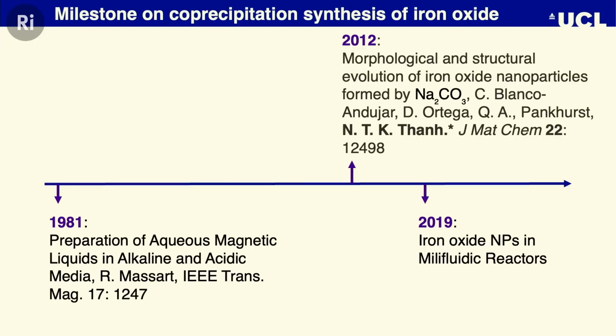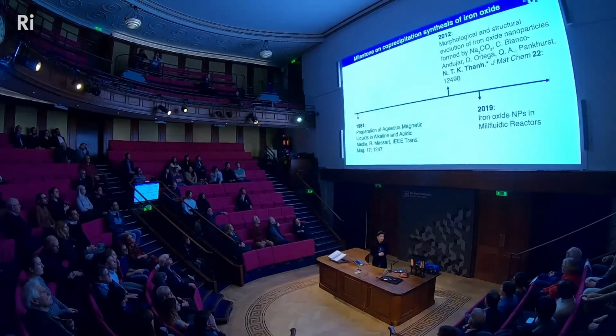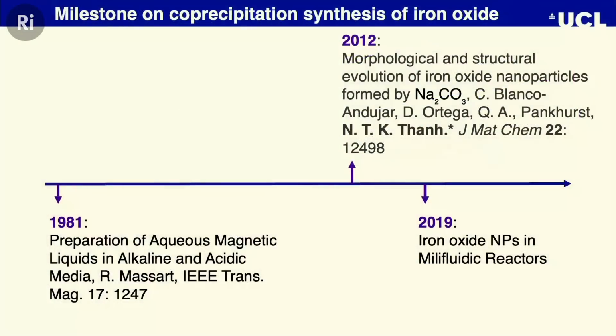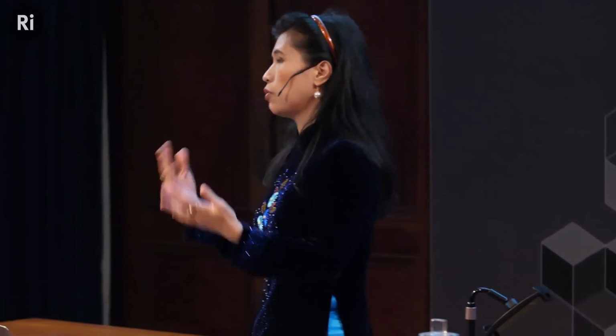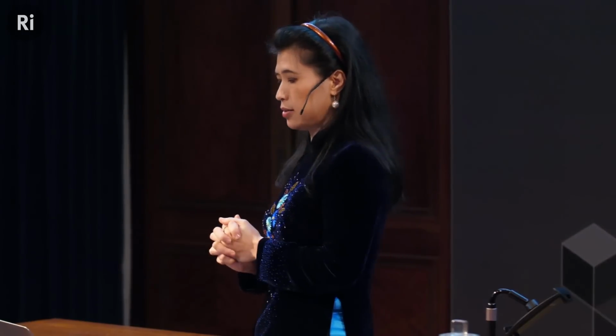Unlike gold, which Faraday made as gold nanoparticle in solution in 1856, it was only in 1981 that René Massart published the paper using two salts, ferric iron and ferrous iron, with ammonia, and he formed the co-precipitation method for forming the nanoparticle. They did the characterization by XRD, and they also found the size to be 12 nanometers.